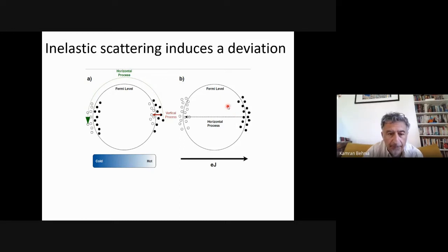If you are measuring thermal transport, you create a temperature gradient across your Fermi sea. So in that case, you are interested in the way heat is carried by this difference between occupied and unoccupied states. So in addition to these horizontal processes, you have also vertical processes. In the case of electrical conduction, where the charge is carried by particles which are focused at the Fermi surface, you only have these horizontal processes.